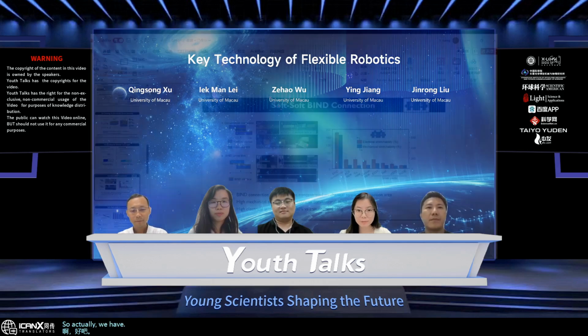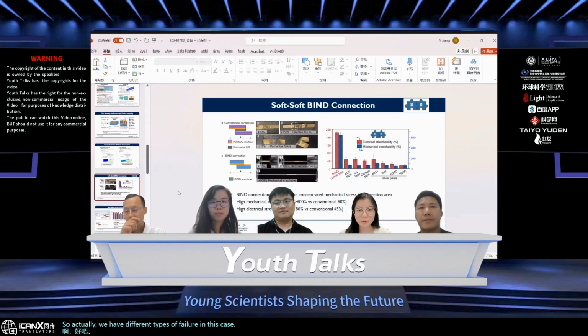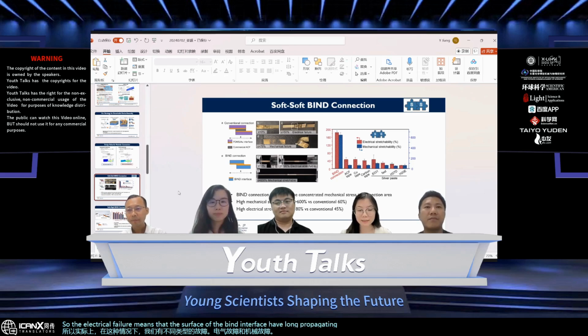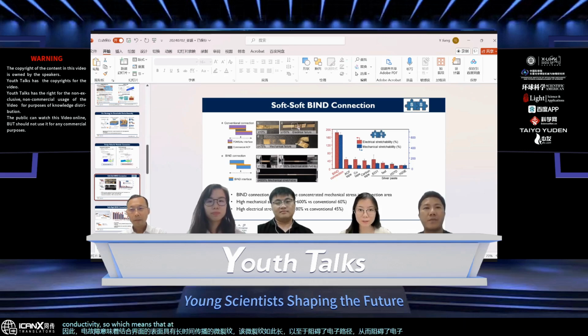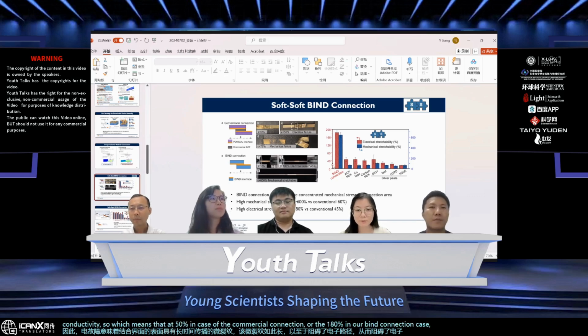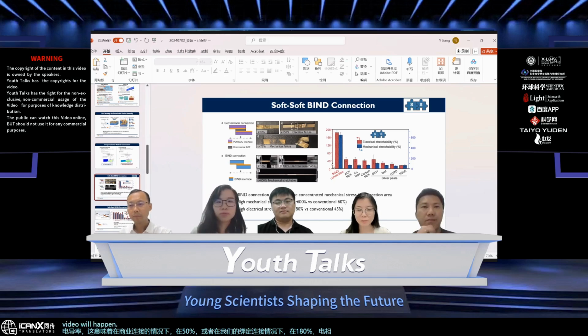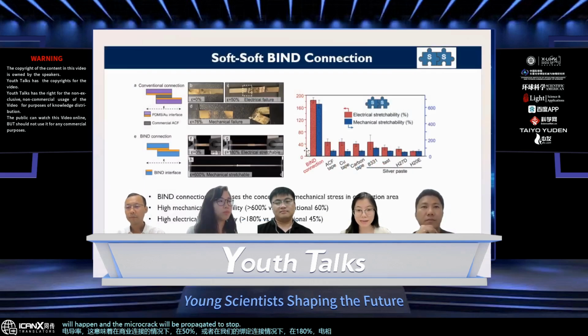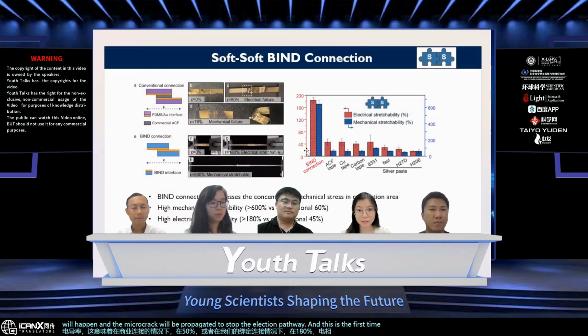Okay. So actually, we have different types of failure in this case, both electrical failure and mechanical failure. The electrical failure means that the surface of the bind interface has long propagating microcracks that hinder the electron pathway, so that they hinder the electrical conductivity. This means that at 50% strain in the case of the commercial connection, or 180% in our bind connection case, the electrical failure will happen, and the microcrack will propagate to stop the electron pathway. And this is the first type of failure.